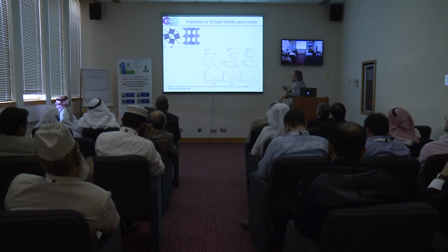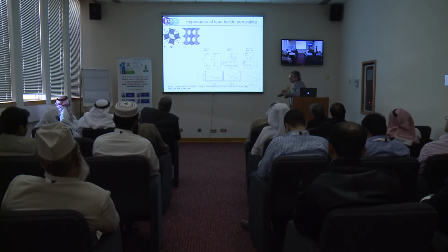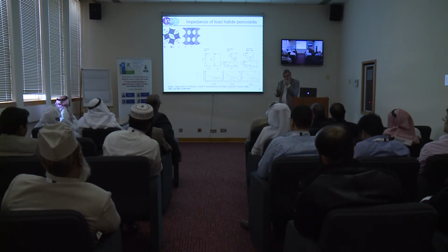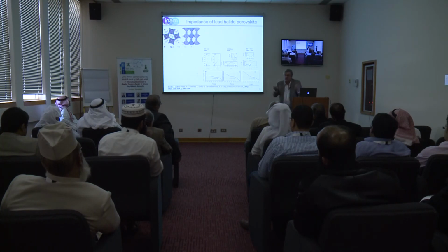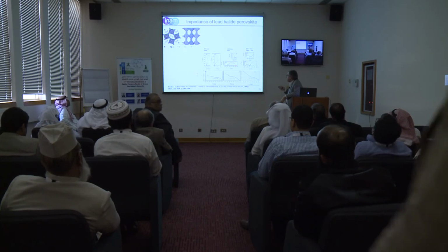So we are doing, again, the impedance spectroscopy, and I explained before, for example, that we typically have 3 arcs in a solar cell. The arc in the middle is the important one, because this is the accumulation of electrons, and then you have one arc at higher and one at very low frequency. This is normally something of contacts, depending on electrochemical contacts. But at this moment, this interpretation is not settled. We wrote some papers, but they have to be taken with a lot of caution.